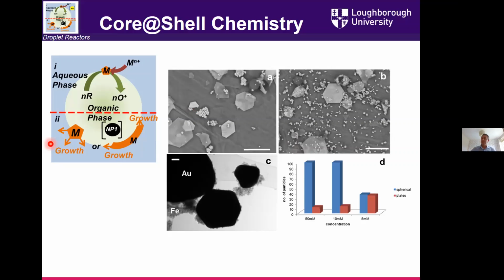But we did try to do that process anyway, regardless of what was happening with the gold, by adding some iron oxide particles in there. It didn't change the chemistry. So the gold still made the same products, but we were able to at least coat those gold with iron oxide. So all of those particles that you can see in those images have been extracted via handheld magnets. They've got the iron oxide on the outside. You can efficiently remove your product from your reaction pot, but it wasn't that core shell process that we had going on. And so this was really the first insight.